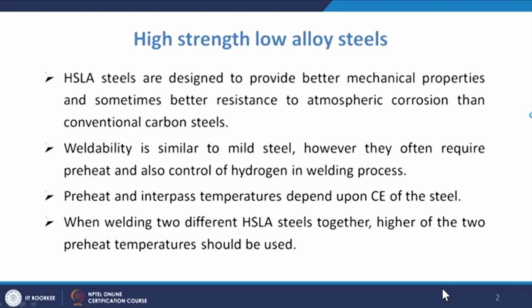Okay. Preheat treatment and interpass temperatures depend upon the carbon equivalent in the steel. If the carbon equivalent is high, we have to increase the preheat and interpass temperatures. When welding two different high strength low alloy steels together, the higher of the two preheat temperatures should be used. If we are using two different steels, whichever has the higher preheat requirement, that preheat we have to provide.